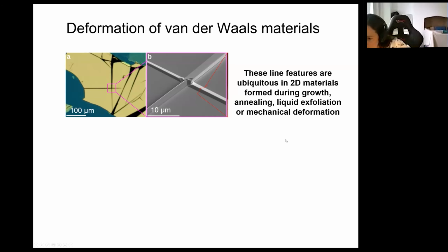Can you see any questions I missed? Yeah, so if you scroll up, there's, for thick graphite, is there a heating effect during ion irradiation, from Baoming Wang at MIT? I'd say it's hard to tell about heating in a TEM. We never saw any evidence of heating, and generally in the TEM imaging mode, we're keeping the electron dose pretty low in order to try and remove any effects of electron beam induced changes. Graphite's also a very good conductor, so often it's the secondary electrons that are causing the local heating and build-up, if there are any, and they get taken away very quickly by the graphene. So we didn't see any heating. We don't believe that that's a significant effect.